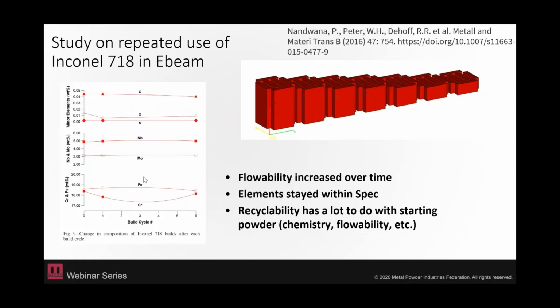This means these powders are recyclable, but they determined that, you know, they actually did start with some really nice powder, and that might be a reason why they had such good results. So that's just something to keep in mind. Like we said before, the powder that you start with is a big factor.